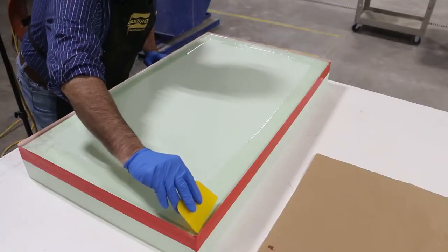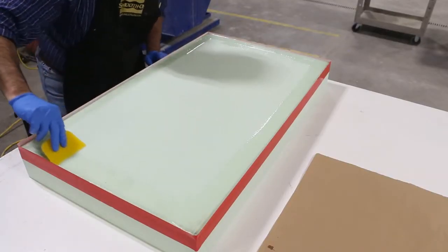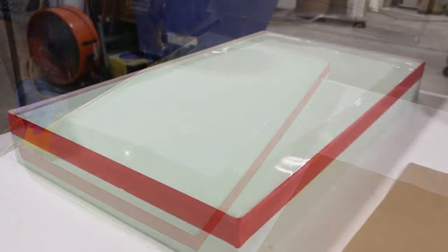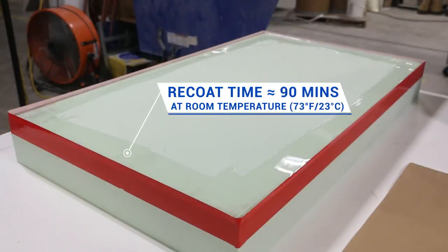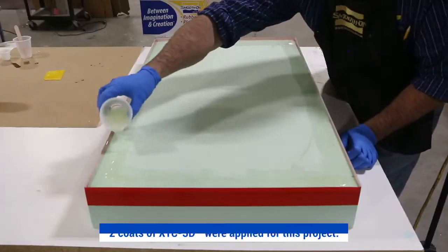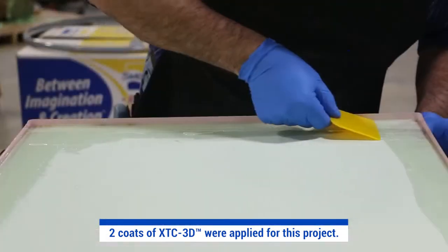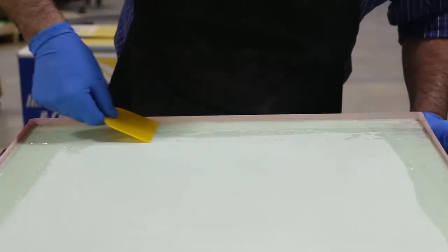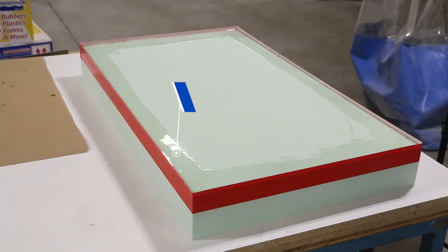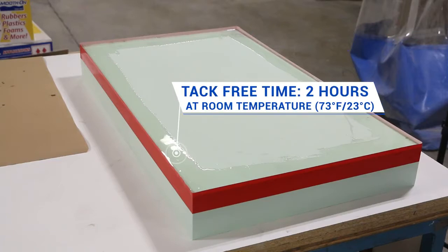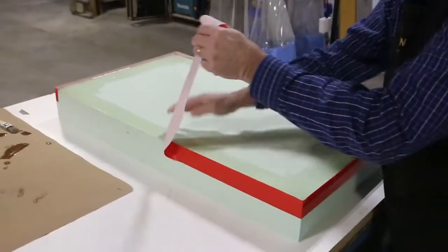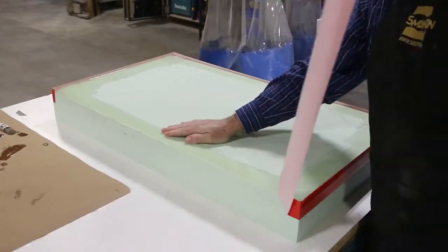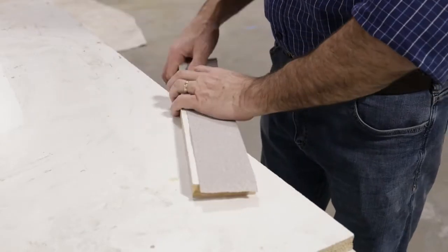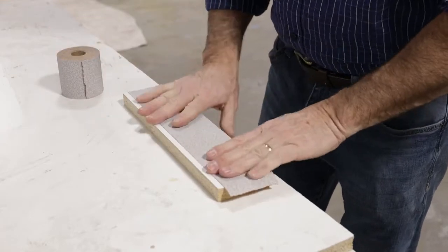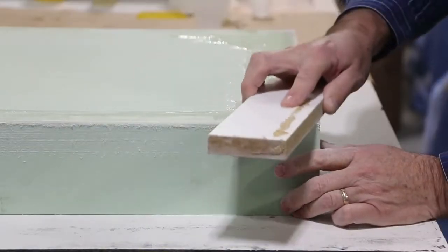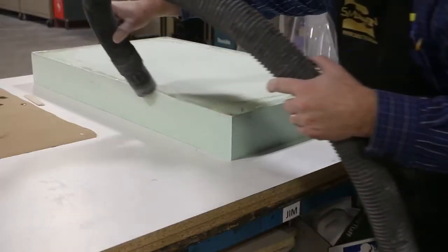A flexible spreader is a good way to quickly distribute the epoxy evenly. Recoat time is approximately 90 minutes if more than one application is needed to establish a uniform edge thickness. Once the edge is coated uniformly, allow to cure until tack-free. Once tack-free, remove the tape and remove the meniscus by sanding flat. Clean loose debris by vacuuming.